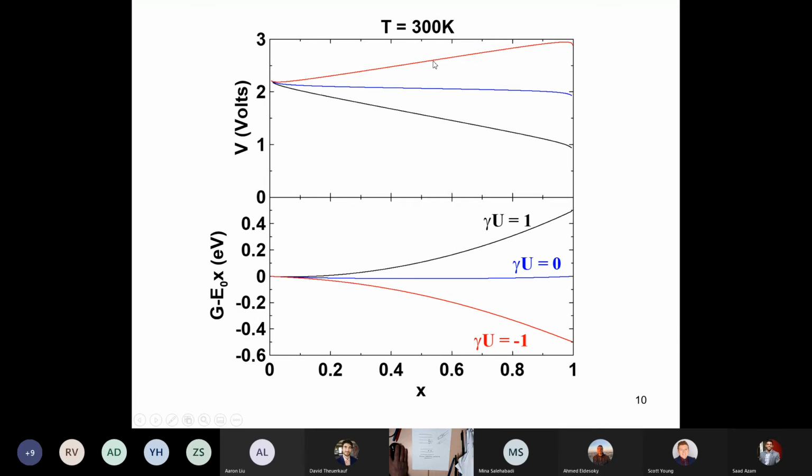All right, so now the question for us to figure out is what happens in the case where one has this attractive interaction, the red curve. This is where lithium atoms attract one another. Well, any system will attempt to minimize its free energy at all times. So if you spread the lithium randomly on the sites, which is the assumption in mean field theory, you'll follow this red curve. This is what the free energy does.